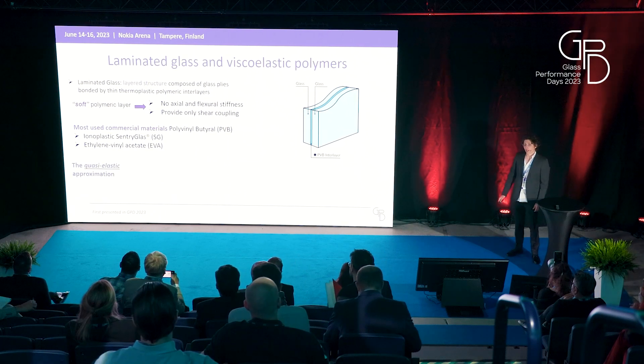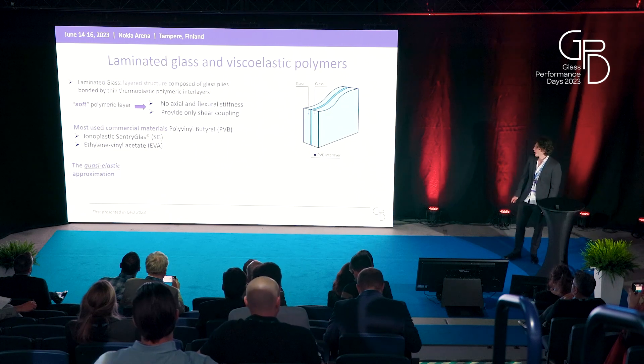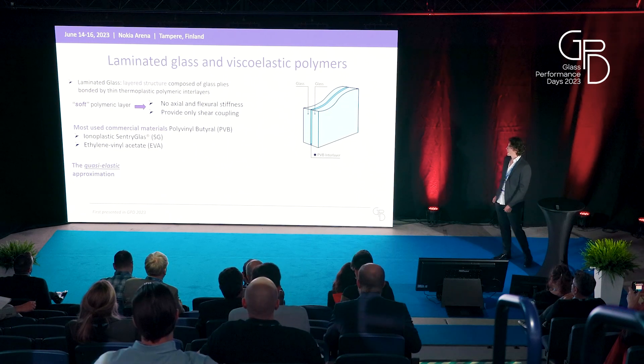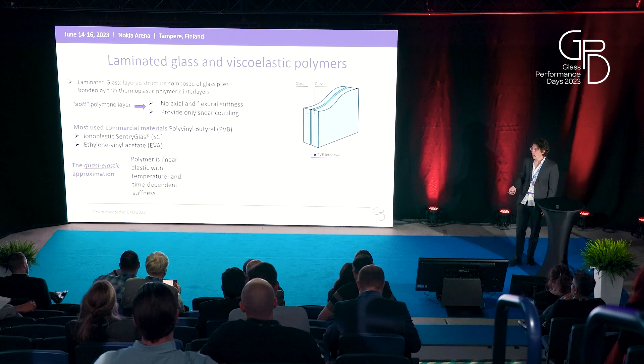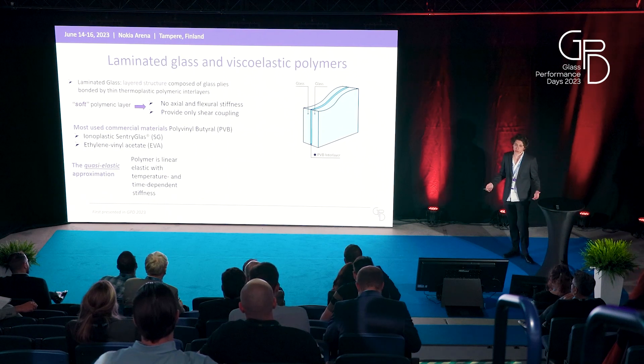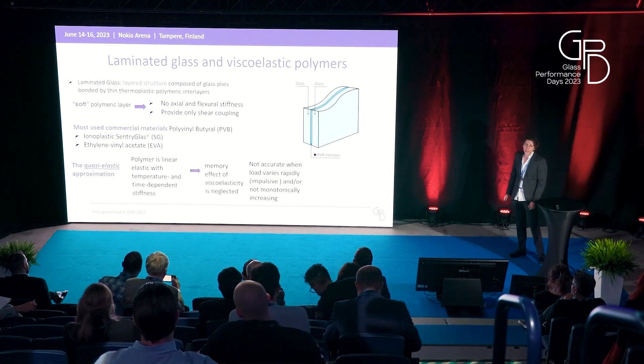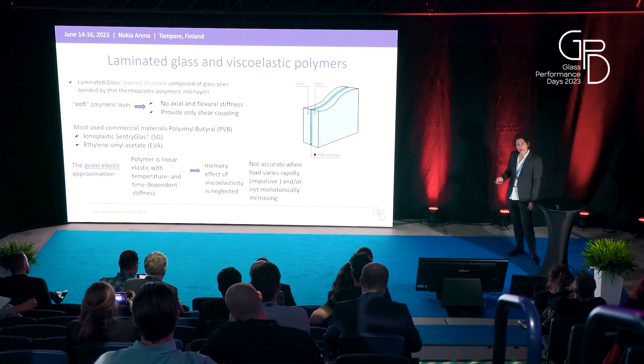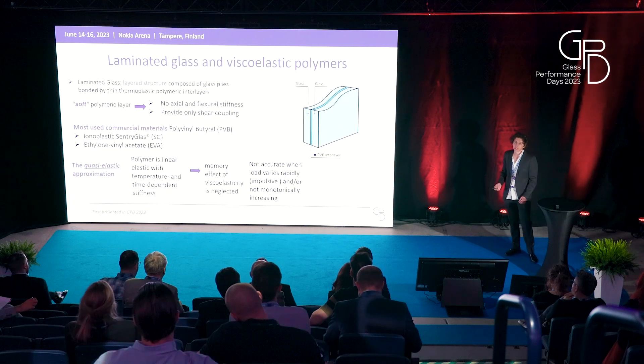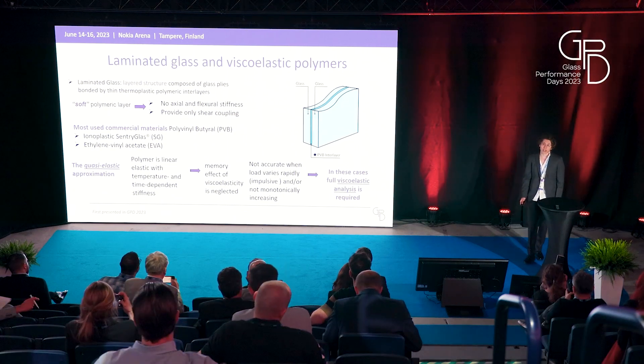In many engineering applications, the quasi-elastic approximation holds. That means that the viscoelastic memory of the polymeric material is neglected, and the stiffness depends only on the load duration and temperature — values that can be found in tables. But this model is not always accurate, because if the load varies very rapidly or is not monotonically increasing, this approximation does not hold. So in our study, a full viscoelastic analysis is required.